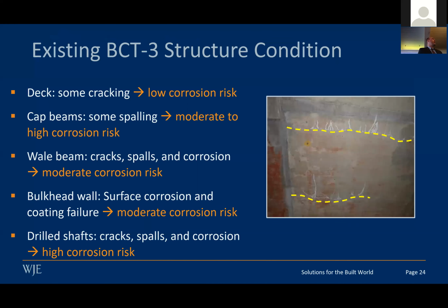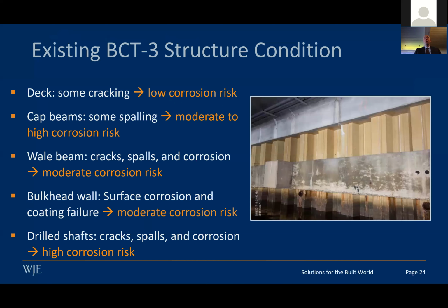Overall, if I just summarize what we saw really quick, the deck had a little bit of cracking in it. It's well above the water level, so it doesn't see the same exposure. And so all of our NDE indications were showing that this is a low corrosion risk. We had a little bit of efflorescence, but not too much. But you start going down lower towards the water line, we saw a lot more corrosion damage, a lot more potential for that risk of corrosion.